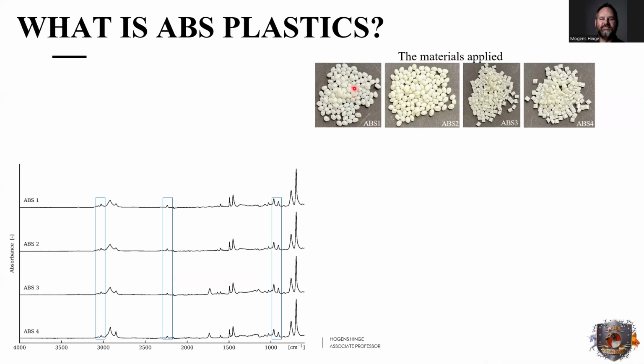So what did we do? We took 4 commercial vendors' plastics, all ABS, that should have approximately the same properties. And then these materials were subjected to an IR measurement, and therefore we have ABS1, which is vendor number 1, and that has an IR trace here. Then we have ABS2, which is vendor number 2, that will have a trace here, then versions 3 and 4 down here. So in this way, we have the different vendors and named them ABS 1, 2, 3, and 4. I have also marked some blue squares here, which is where the interesting part goes on.